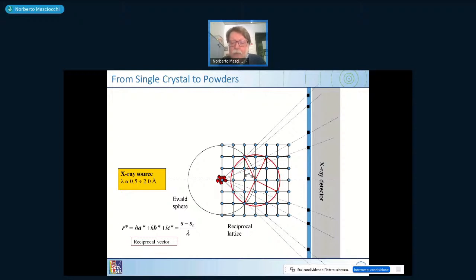So all points which are lying on this circle, or in principle on the sphere in 3D, are in a diffraction condition. So now you take two spheres, it's called the Ewald sphere, for which you see only the circle, and you take the red sphere and you intersect the two spheres. What is the ensemble of points in which the two spheres coincide? Exactly on this circle. So the two spheres define a circle. It's the rim of a torus. And then all the points which are lying there are in reflection condition.